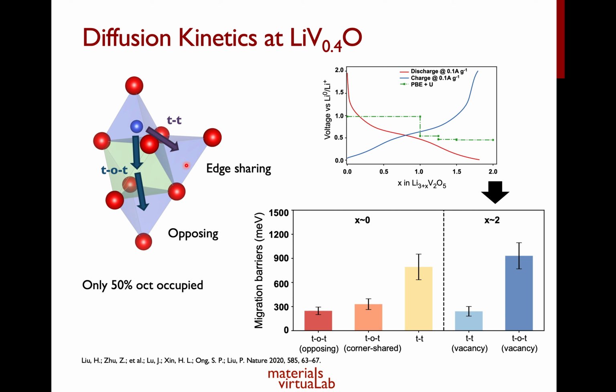So again, we look at two possible mechanisms. One is to just do the direct T to T hop. The difference being now that this direct tetrahedral to tetrahedral hop is no longer hopping between two occupied octahedrals. The likelihood is that the two octahedrals are actually unoccupied, because 50% of the octahedrals are unoccupied. Now, the other mechanism that we investigated is our standard layered diffusion process, in reverse.